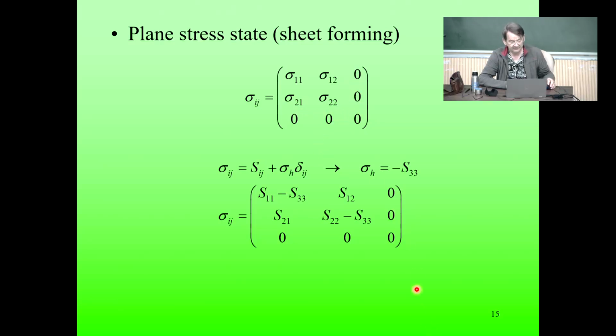We have hydrostatic stress and also the deviatoric stress. The total of the deviatoric stress plus hydrostatic stress is making the true stress, sigma j. And applying this equation on this component, one finds immediately that the hydrostatic stress value is equal to minus S33, where S is the deviatoric stress tensor. So finally, this is the total stress tensor for plane stress state.